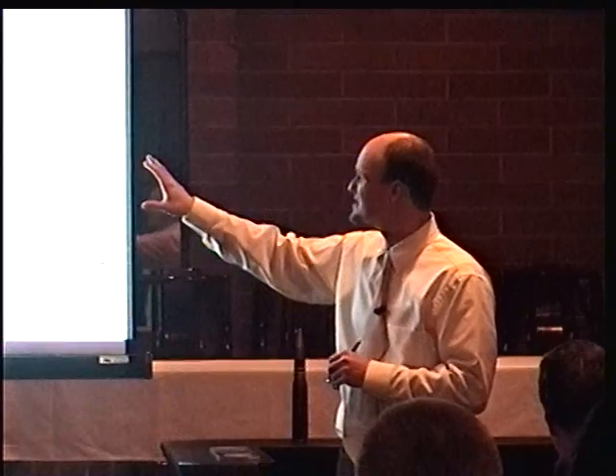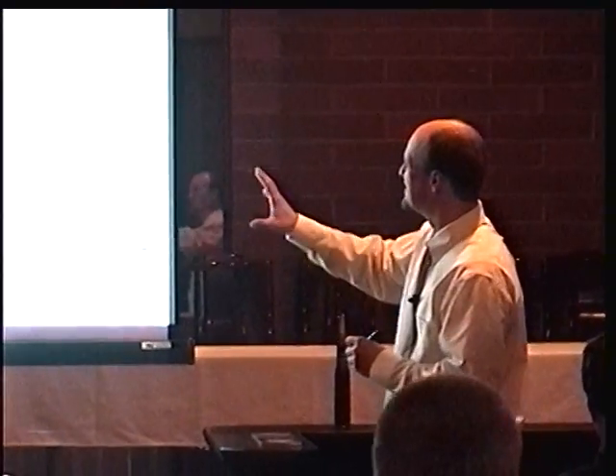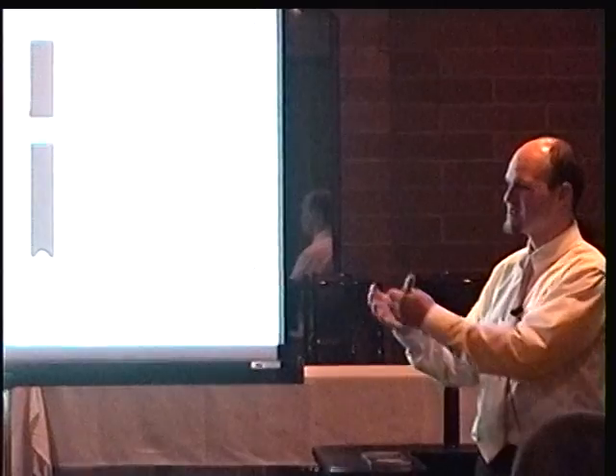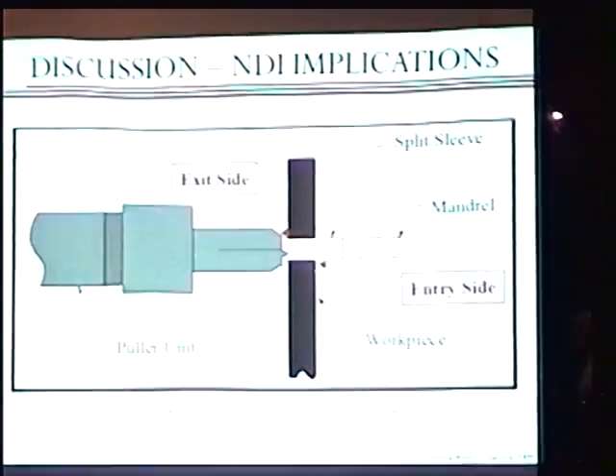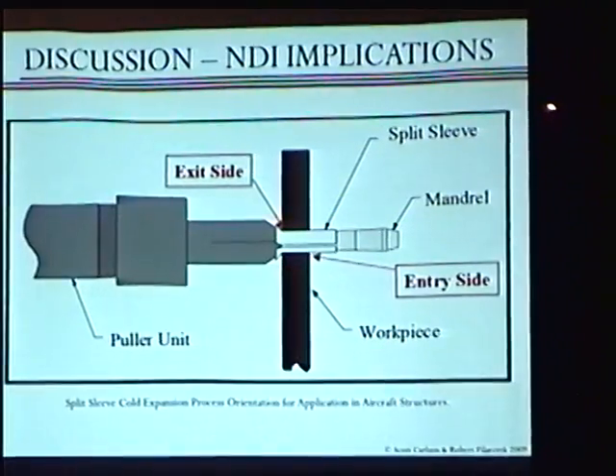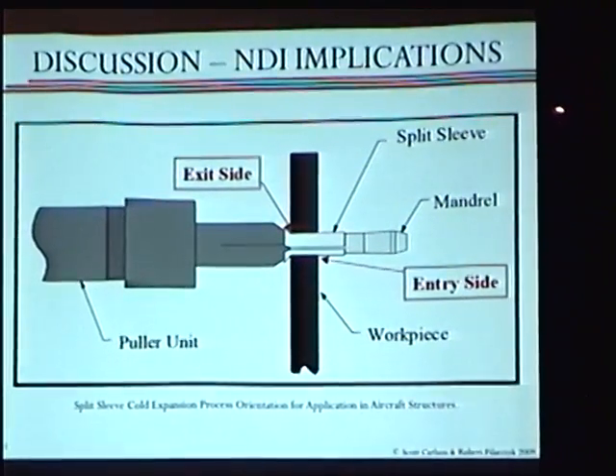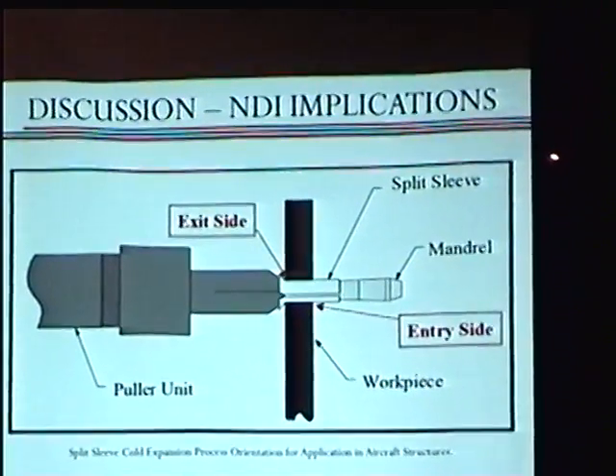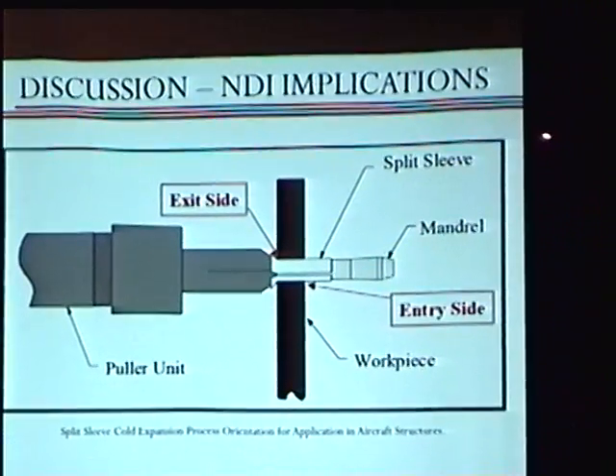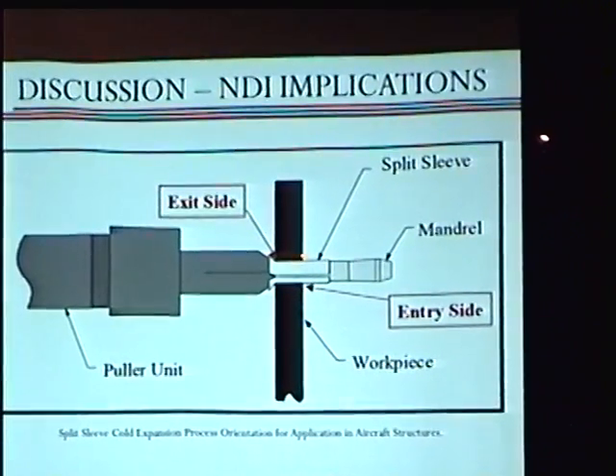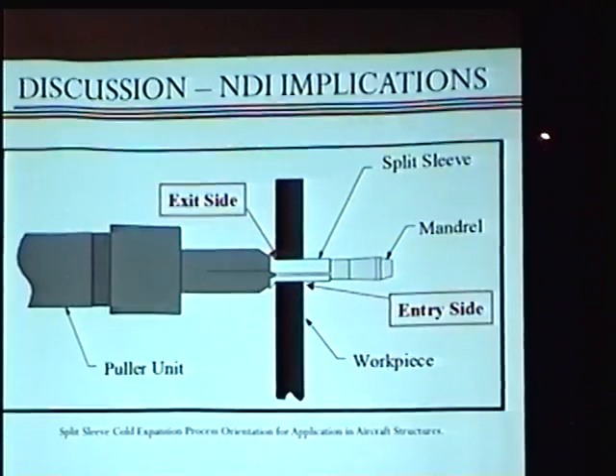Really what this process does is not just a simple two-dimensional residual stress field. It varies depending on how it was processed. Because of how the material flows and how you pull that mandrel through, the residual stress on this side of the component is different than on this side. It's a three-dimensional residual stress field. What that means is the cracks are going to grow differently on this side than on this side, and that's important.